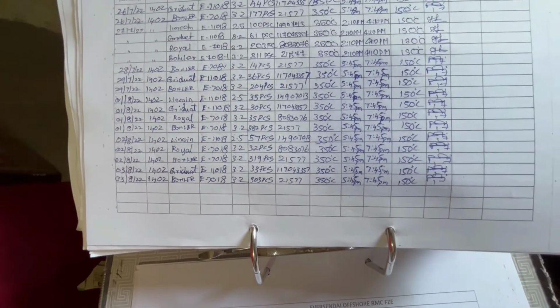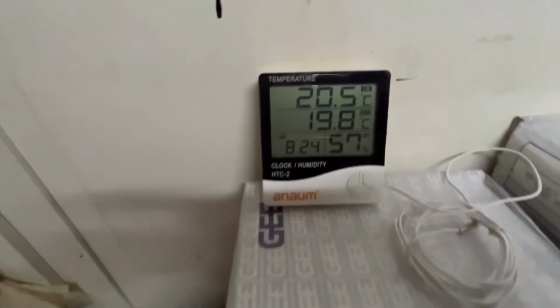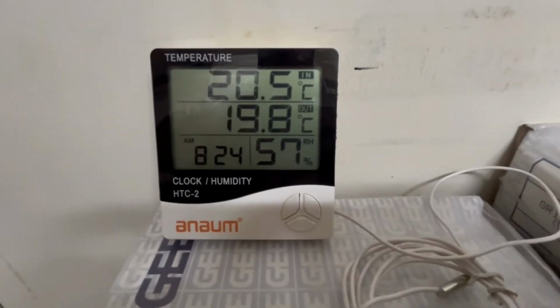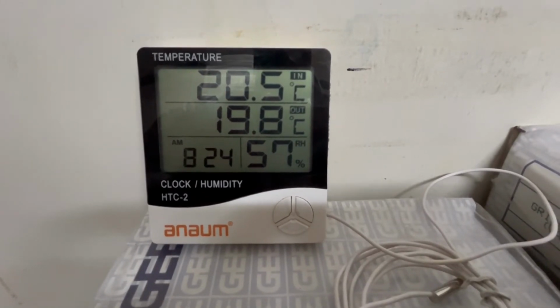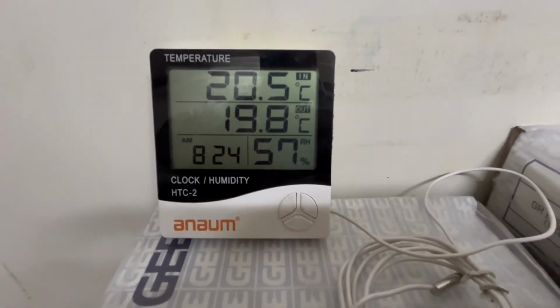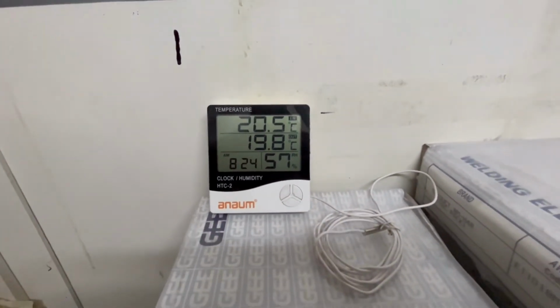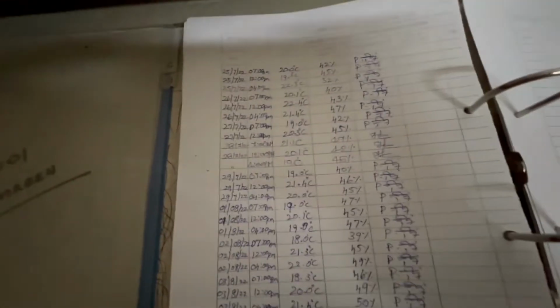So what time you have put the electrode in the baking oven, and what time we have removed, including, and then we have put the holding temperature. So you need a very properly calibrated temperature gauge here, which can also show you RH, relative humidity. So you can see this is a calibrated gauge we have put here.